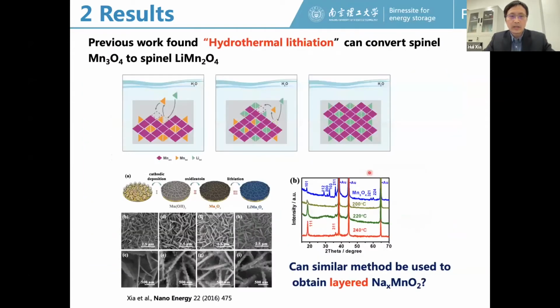So in another work, we used hydrothermal lithiation to convert the spinel Mn3O4 to the spinel lithium manganese oxide. Then we started to think if we can use a similar hydrothermal sodiation method to prepare this layered sodium manganese oxide with a high sodium content.